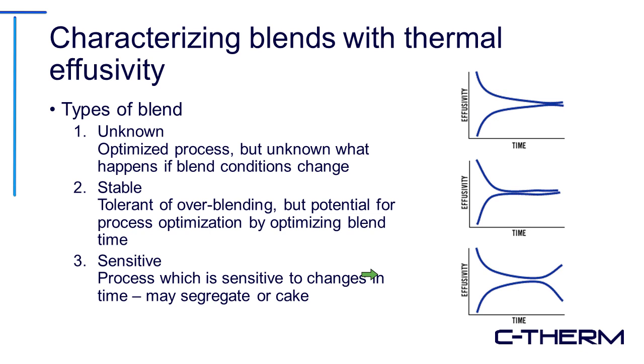So that's a really good case scenario, because a stable blend is not going to be at risk of segregation, and it's not going to be very sensitive to slight variations in the process conditions. The worst case scenario, and quite a bit more common than the stable blend, is the sensitive blend. And this is a process where the blend itself is sensitive to blending conditions and to changes in the amount of blending time. The product may segregate, or you may get caking if you go too long.